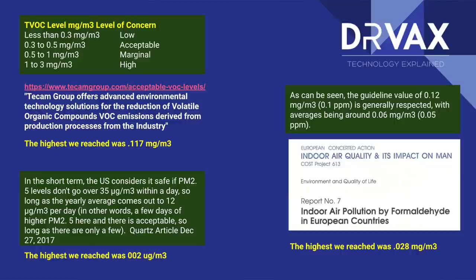And I was at 0.117. So 0.117 is less than half of 0.3. Half of 0.3 would be 0.15. So even at the worst reading, PETG, at least the PETG that I did this test with, which was actually Hatchbox PETG, did not give off more TVOC fumes than is considered absolutely safe.